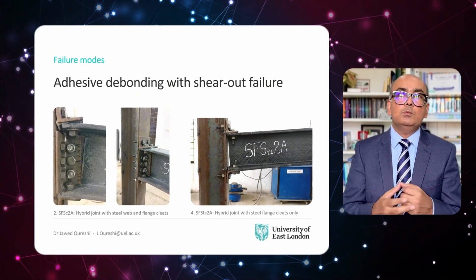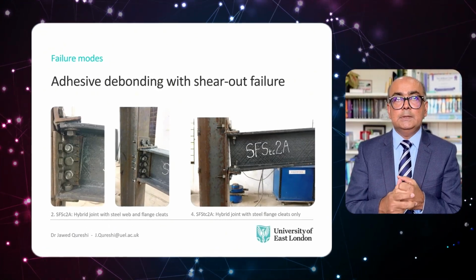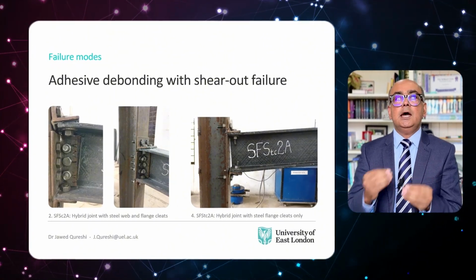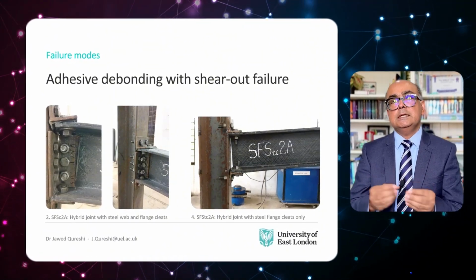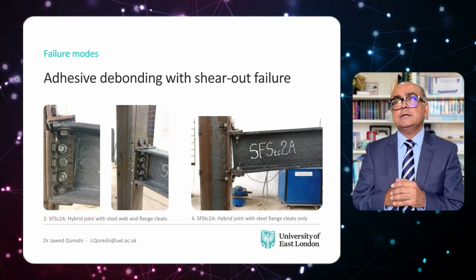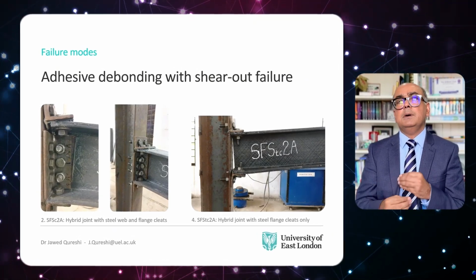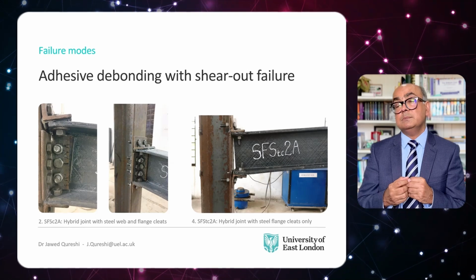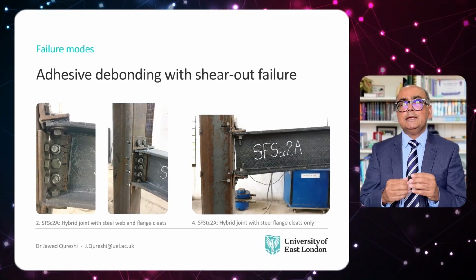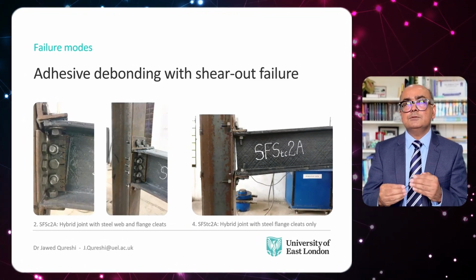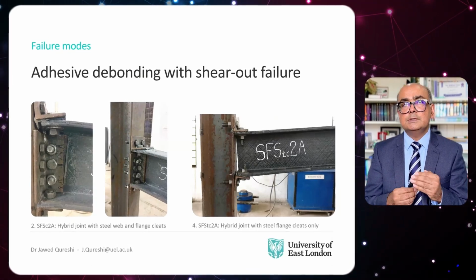The second failure mode observed was adhesive debonding with shear out failure. And this failure happened in hybrid joints with steel cleats. The failure started with adhesive debonding followed by shear out failure of beam's bolted region. Some cracking at the web flange junction of the beam was also observed in this failure mode.